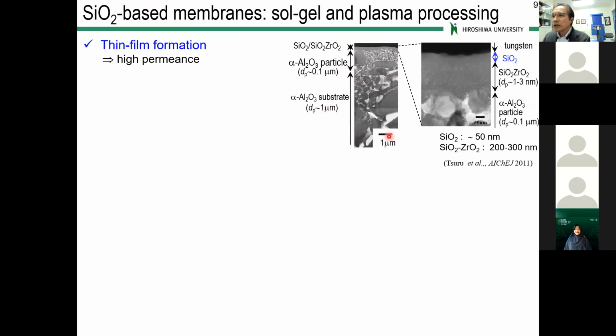This part is a substrate, an alpha alumina substrate. These particles are the alpha alumina particles of the substrate. This was 1 micrometer, so this space is the pores. On this substrate, we prepare alpha alumina particle layers. Here you can see some small particles, which have an average pore size around 100 nanometers.